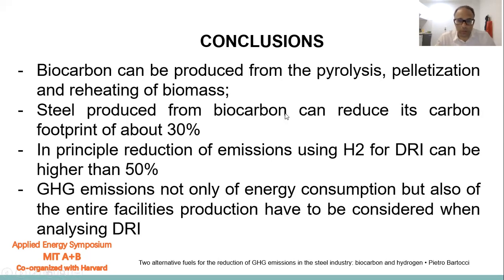Coming to the conclusion, biocarbon can be produced from the pyrolysis, pelletization, and reheating of biomass. Steel produced from biocarbon can reduce its carbon footprint of about 30%. In principle, reduction of emissions using H2 for direct reduction of iron can be higher than 50%. So here we see a comparison of what we can consider A technology against B technology, because this will probably come in the future. And greenhouse gas emissions for hydrogen direct reduction of iron should not consider only energy consumption, but all the emissions due to the new facility which are needed for this innovative project.